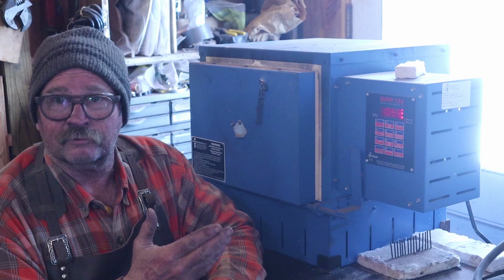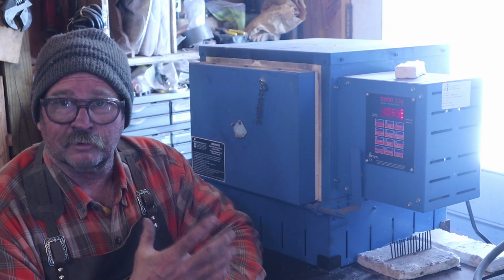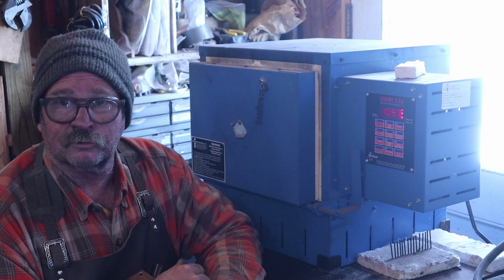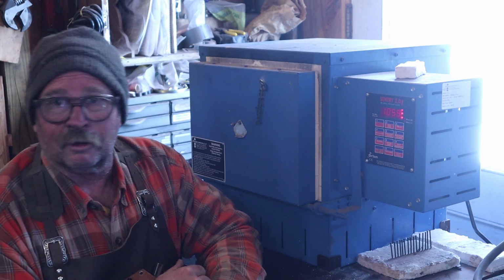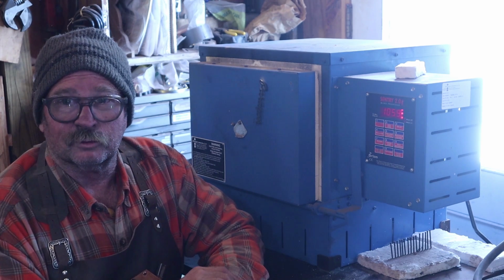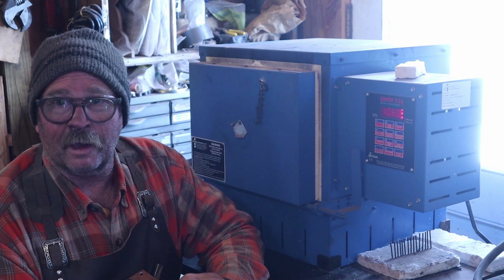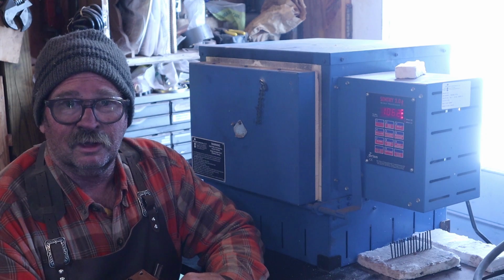Then it'll come up to 1725 degrees. That's the proper quenching temperature for S7. I'll also let it soak for another 20 minutes once it gets there, make sure it's good and hot all the way through. Then I'll bring them out. I'm going to let them air cool. Typically S7 is an air cooling steel, although something this heavy, you can oil quench it.